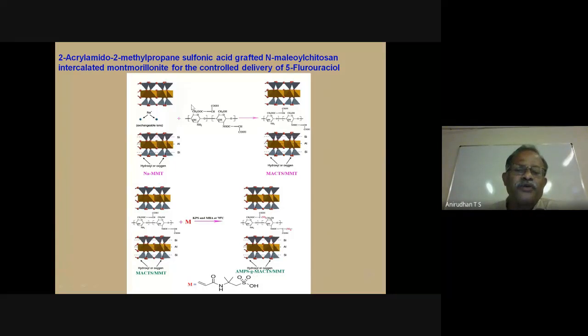Once again, I come to this point. Now, this is a clay montmorillonite where you have a layer structure. We have silicate layers. So alumina octahedra and silica tetrahedra are arranged in layers, and in between these layers we have a cavity associated with sodium, calcium or potassium counter positive ions. This is the spacing in between two layers, and we have 12 Angstrom cavities there. So we utilize these cavities in between the alumina octahedra and silica tetrahedra layers, and we have introduced 2-acrylamido-2-methylpropane sulfonic acid.